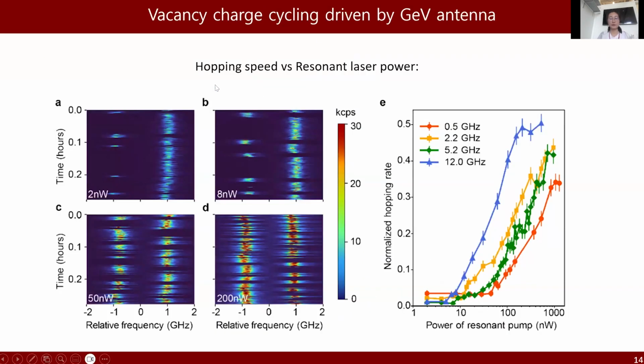Now we can make use of this property to experimentally quantify the near field enhancement from GeV antenna. The left figure is the time-dependent PLE spectrum of a hopping GeV. As we can see, we increase the laser power from 2 nanowatts to 8 nanowatts, and we see no change in the hopping speed. But as we keep increasing the laser power to about 50 nanowatts, the hopping speed has changed. This indicates a threshold power to drive the charge cycling of carbon vacancies. It means that the laser power must reach this threshold so that the near field generated by the GeV is enough to drive the charge cycling of the carbon vacancy.